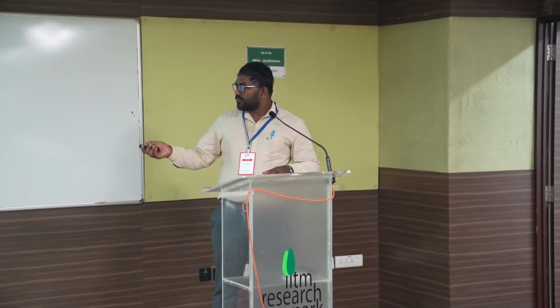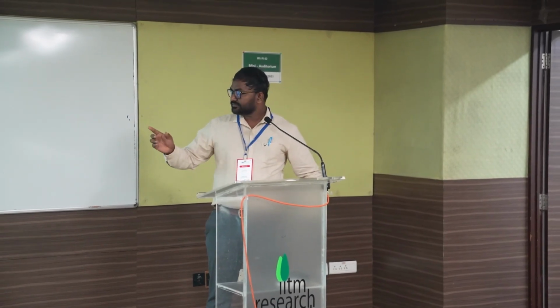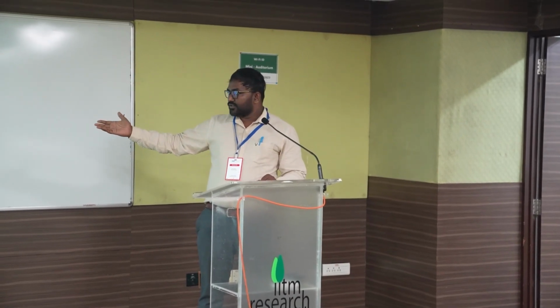And the reason why we are excited about this additive specifically is that this one additive, when used at a weight percentage of 0.2 with respect to cement, can positively influence up to 6 properties in concrete. So for traditional construction, M30 is the most preferred design mix. M30 is a grade of concrete which refers to the strength. In a traditional M30 grade concrete, adding 0.2 weight percentage of Terracops graphene helped us reduce the water permeability and chloride ingress. These are two parameters which directly correlate to how good the reinforcement's durability would be over an extended period of time.